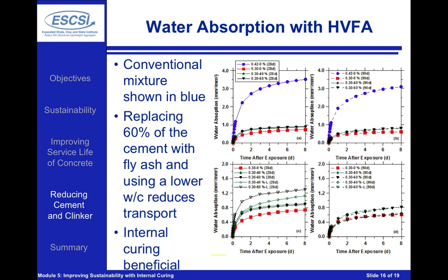Another way that we can look at this is we can essentially start to look at comparing that conventional mixture that we saw with these lower water to cement ratio mixtures where a high volume of cement has been replaced with fly ash. And we can see here pretty dramatically in the graph at the center, which was taken after 28 days of curing, and the graph on the right-hand side, which was taken after 90 days of curing, that by moving from a 0.42 water to cement ratio, which is the blue line, to our 0.3 water to cement ratio, either pure cement, which is the red, or cement where 40% of the cement has been replaced by fly ash, or 60% of the cement has been replaced by fly ash, as we see with the dark line, we see a substantial reduction in fluid transport.